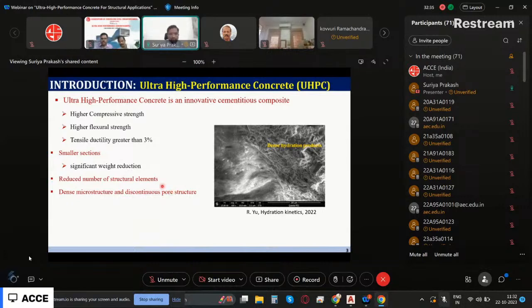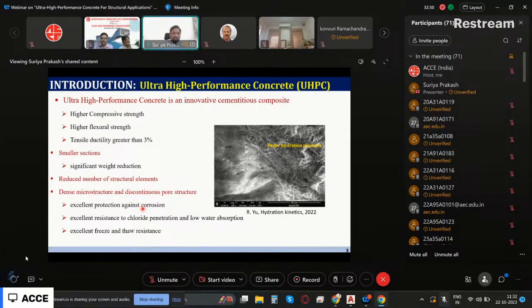If I'm able to make this pore structure discontinuous, then I make the concrete very, very durable. So this is the advantage. It gives excellent protection against corrosion, excellent resistance to chloride penetration, and low water absorption. These are all the advantages. And also it gives you excellent freeze and thaw resistance.